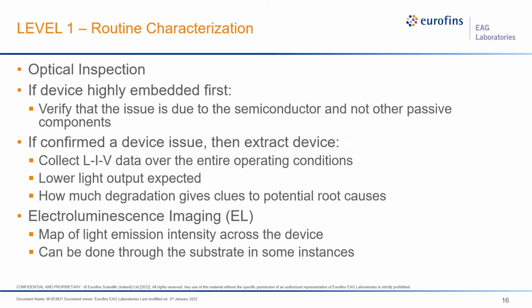In this case, lower light output has occurred. We actually have no light output anymore. So how much degradation there really is gives you clues to potential root causes and allows you to create a feedback loop within the different levels of analysis you're doing. And then in a lot of cases, we can use electroluminescence imaging on devices that are still at least partially functional to directly map where the light is being quenched, for instance, here.